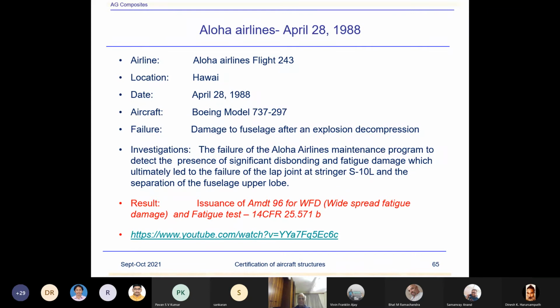Criteria, final loading. Aloha Airlines Flight 243, location of failure Hawaii, April 28, 1988, Boeing model 737-297, and the failure was damage to fuselage after an explosion, decompression. Investigation led to the failure of Aloha Airlines maintenance program, because during maintenance program, they could not pick up the damage which was already propagating. Detect the presence of significant disbonding and fatigue damage, which ultimately led to the failure of lap jointed stringer S10L and separation of the fuselage upper lobe.